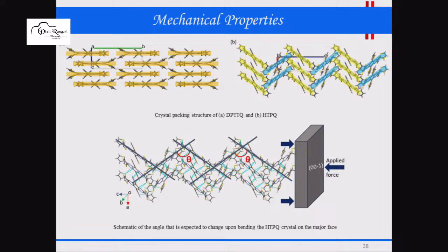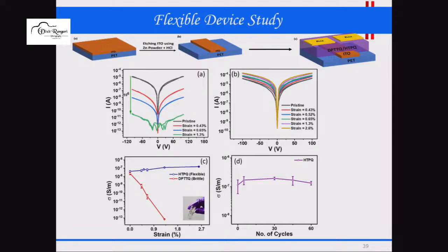Okay, so we thought, can we use this flexibility in making flexible organic electronic devices? We again collaborated with Professor Sena Naik from NISER Bhubaneswar, and he studied this molecule and made the device. You can see in the bottom picture there is a device made on a PET surface, that means a polymer surface, and we can fold that device. By folding many times, he looked at the conductivity of the device made from this crystal, and in the second case the conductivity of the device remains consistent after folding for many cycles. But the first molecule, which we have seen is a brittle crystal, loses conductivity.